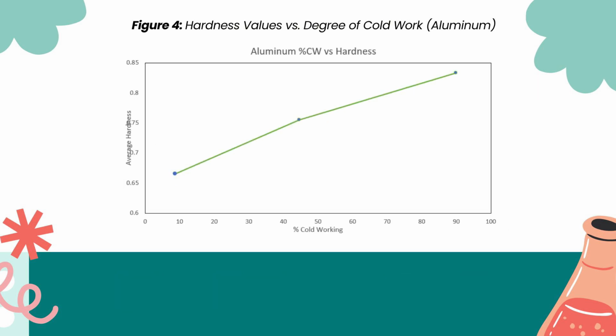Figure 4. If you look at our results here, you'll see a clear trend: by increasing the cold work from 10% to 90%, we've significantly boosted the aluminum hardness. This happens because we are essentially cluttering the atomic structure with dislocations, making it much harder for the atoms to slide past one another. It's a great way to strengthen a part, though we have to be careful not to make the material too brittle for its intended use.